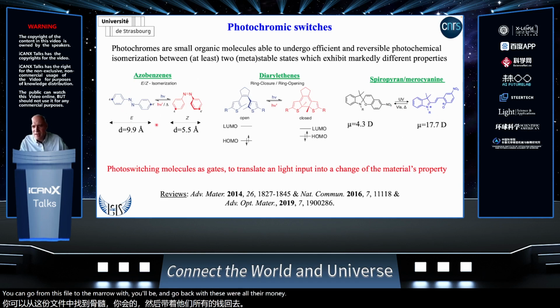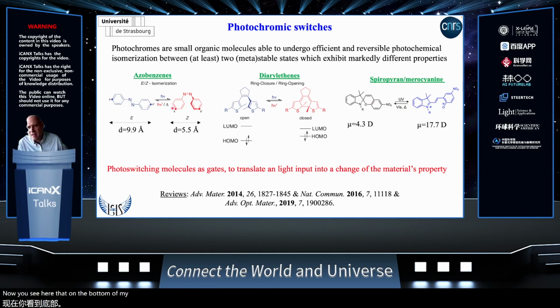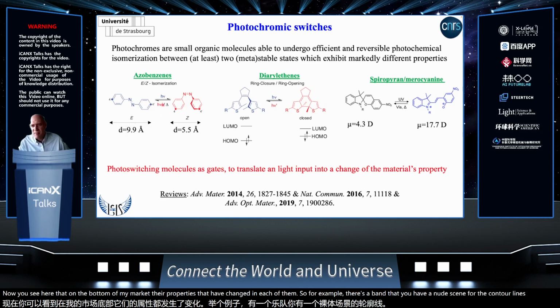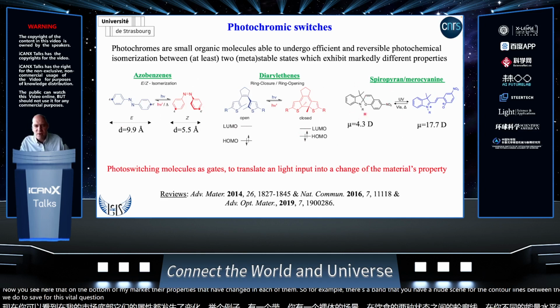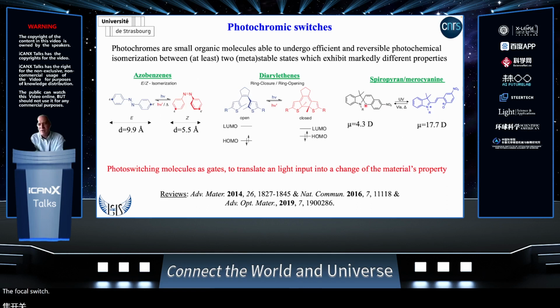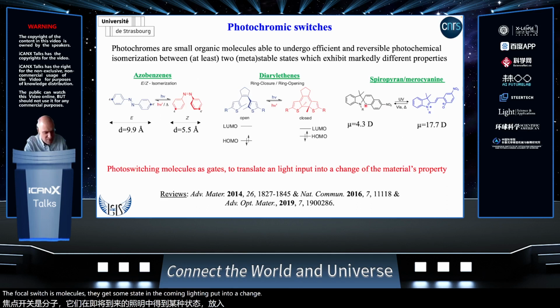Now you see here that on the bottom I marked the properties that are changed in each of them. So for example, in azobenzene, you have a huge change of the contour length between the two states. In diarylethene, you have changes of the energy levels between the two states. For spiropyran, you have a major change of the dipole moment. So the idea is to use the photoswitching molecules as a gate to translate an incoming light input into a change of the macroscopic material.